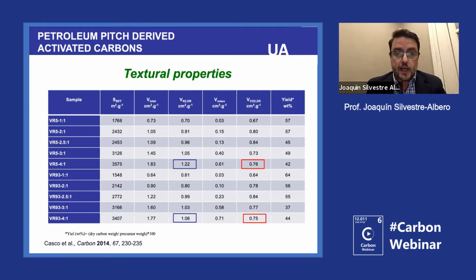And in these specific carbons where we were working with a high activation degree, we were developing narrow micropores, as you can see here, from CO2 Dubinin, and wide micropores obtained from the Dubinin-Radushkevich equation applied to the nitrogen data.